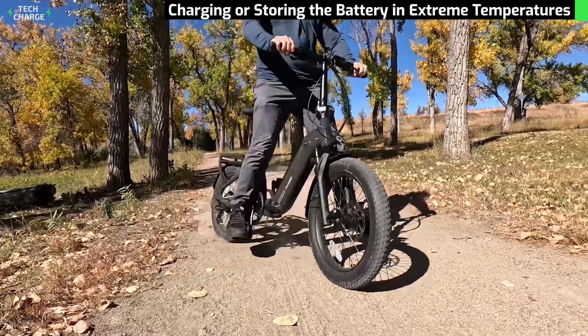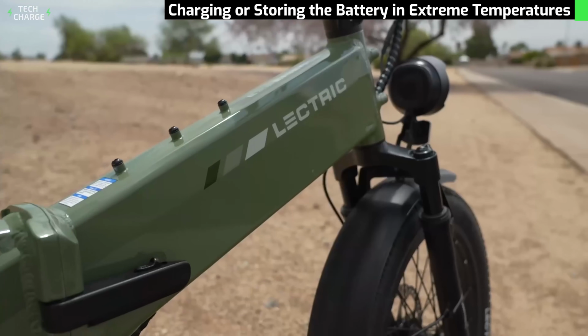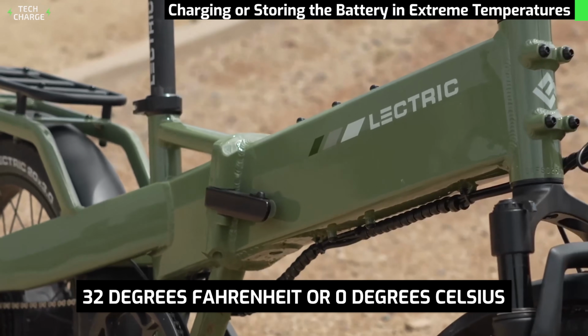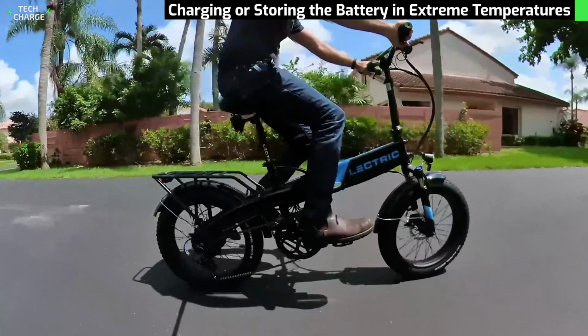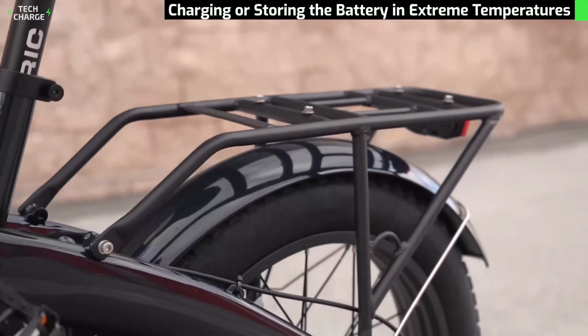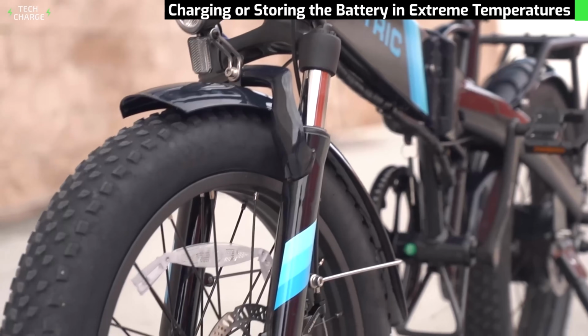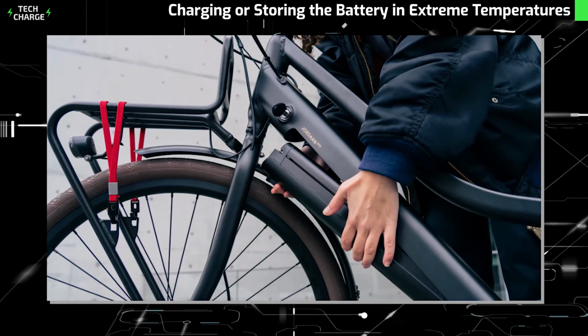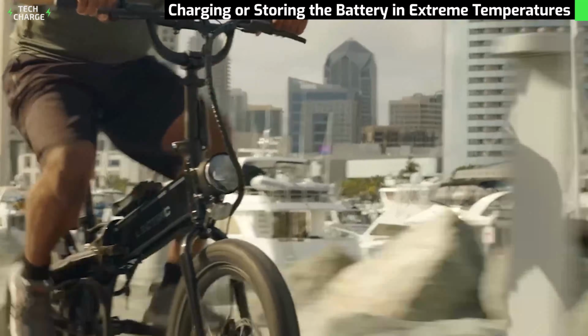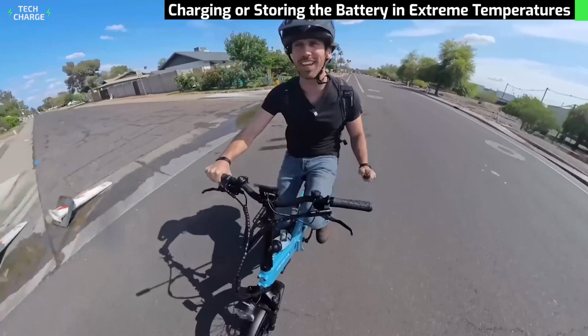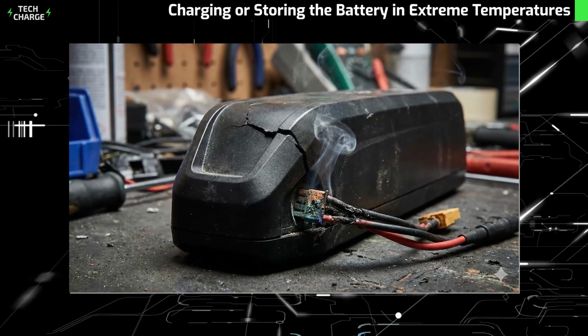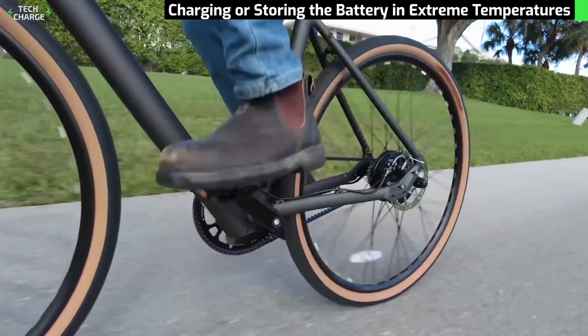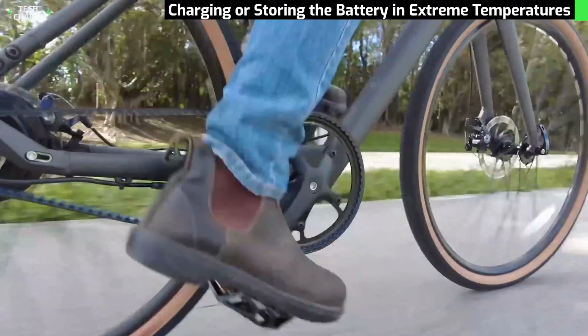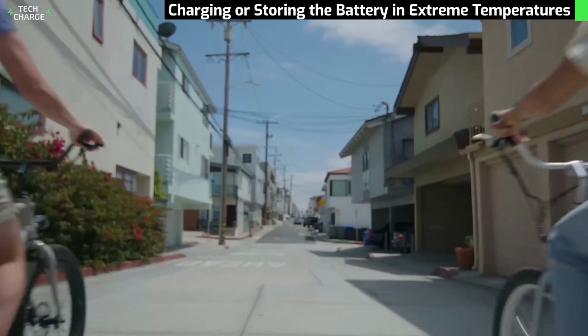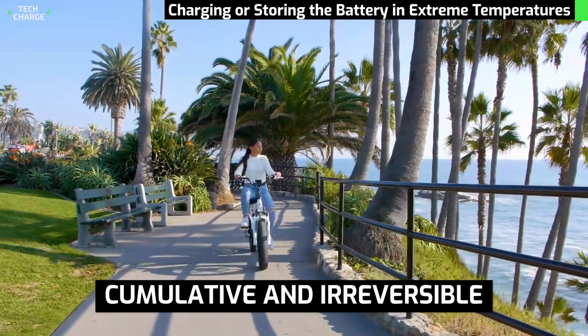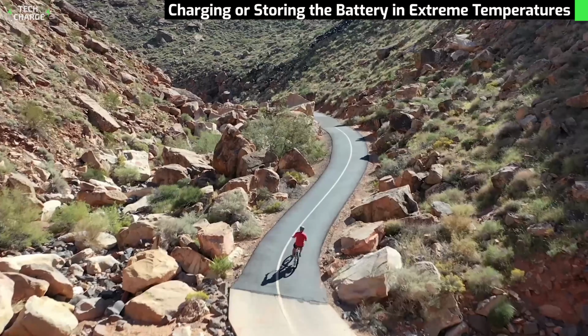The cold weather rule is absolute and non-negotiable. Never charge a lithium-ion battery below 32 degrees Fahrenheit or 0 degrees Celsius. This is considered a cardinal rule by battery engineers because charging below freezing causes permanent, irreversible damage to the cell structure. When you charge a cold battery, lithium ions can't properly intercalate into the anode material. Instead, metallic lithium plates out on the anode surface, forming dendrites, tiny spike-like structures that grow with each cold charge cycle. These dendrites eventually puncture the separator membrane between the anode and cathode, creating an internal short circuit that triggers thermal runaway. This damage is cumulative and irreversible. Every cold charge cycle makes the battery more dangerous.